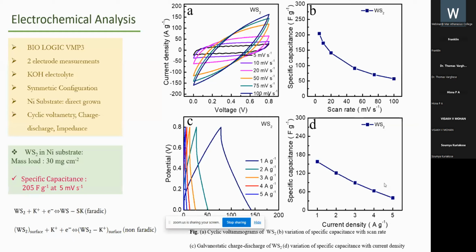The CV shows a quasi-rectangular shape, which indicates the pseudocapacitive property of the material, and the GCD also shows nonlinear behavior, deviating from the rectangular shape. The triangular shape also ensures the presence of pseudocapacitive behavior. The capacitance was calculated, which is around 205 farad per gram at 5 millivolt per second over a mass loading of 30 mg per centimeter square.